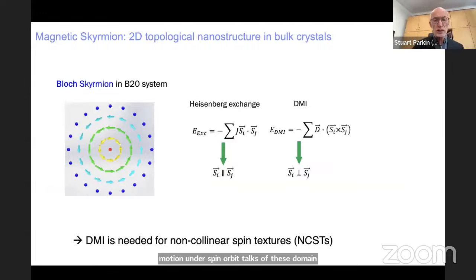If we now go from what was essentially a one-dimensional system of striped domains in a perpendicularly magnetized system to two-dimensional or bulk crystals, then in those systems, the Dzyaloshinskii-Moriya exchange interaction can exist, and it's typically in systems which have strong spin-orbit coupling. And in this case, you can see in this cartoon, it can lead to what is called a skyrmion. And in the so-called B20 system, which is a cubic chiral system, then the nature of the domain walls.